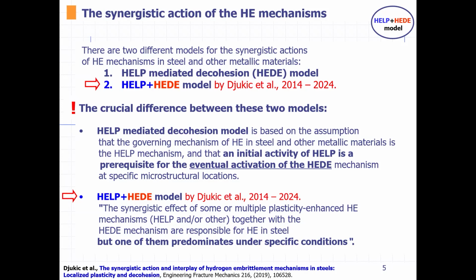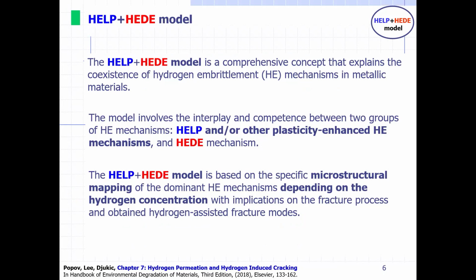That is the difference from the so-called HELP-mediated decohesion model proposed by a group from Urbana-Champaign, Professor Robertson and Sofronis, which pointed out that initial activity of some plasticity-mediated mechanism, particularly HELP, is a prerequisite for eventual activation of decohesion as a final failure mechanism. And we show that it's not always the case, particularly at a very high concentration, higher than the critical hydrogen concentration. So the HELP HEDE model is a comprehensive concept on which several teams, as I presented, now work worldwide to confirm as a unified theory about hydrogen embrittlement in metallic materials.